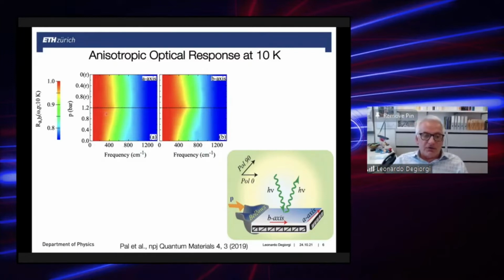Now, the data I'm going to show you now and for the rest of my talk were obtained after the so-called zero stress cooling protocol. It means that we reached any target temperature without applying stress, and then at that fixed temperature, we apply stress in situ, tuning it from 0 to a maximum value, and then releasing it back to 0. Now here I focus the attention on the mid-infrared down to the far-infrared spectral range, because for the optimally doped regime, this was the spectral range where we did discover, first of all, some temperature dependence because of the superconducting phase transition, but also some relevant stress-induced anisotropy.